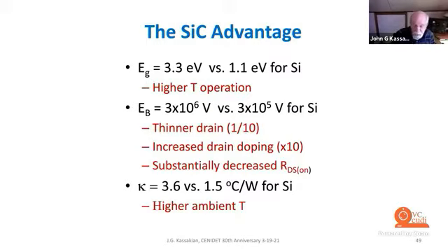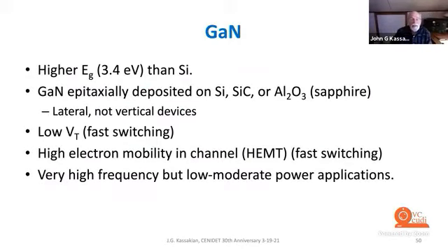So what about gallium nitride? Well, gallium nitride is a much more expensive device. The biggest issue with gallium nitride is that it's epitaxially deposited on a substrate of silicon or silicon carbide or aluminum oxide, Al2O3, which is sapphire. This is because you cannot fabricate so far a native gallium nitride substrate of sufficient thickness to be able to fabricate a vertical power device. So all gallium nitride devices are lateral, not vertical devices.